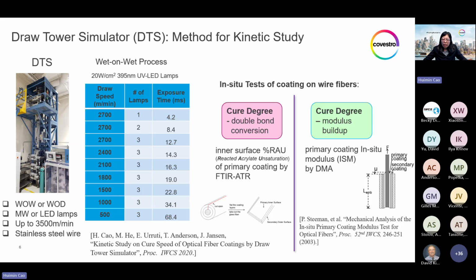Here is to describe again our methodology introduced in our 2020 paper using the draw tower simulator, drawing a stainless steel wire fiber with the same coating process as the actual fiber drawing, wet on wet or wet on dry, microwave or LED lamp, and with the draw speed setting up to 3,500 meters per minute. Very impressive. And for kinetic study, we would set the draw speed and lamp numbers to a series of low to high exposure times in order to capture a complete reaction process.